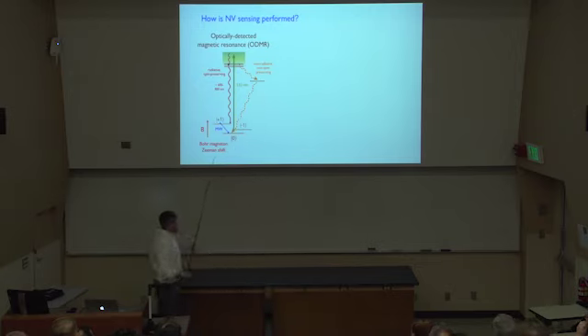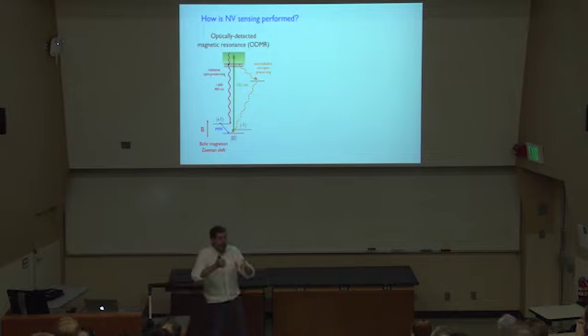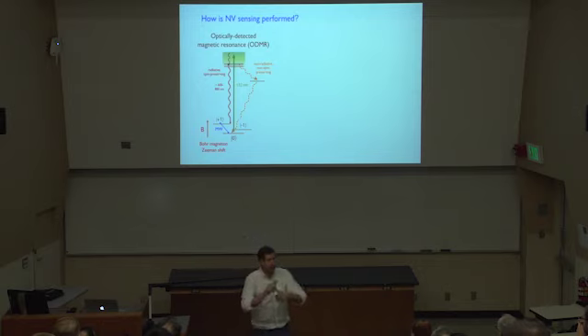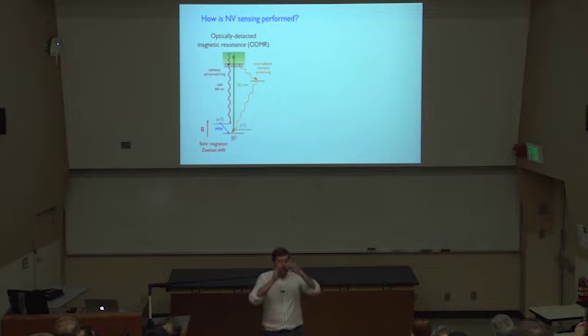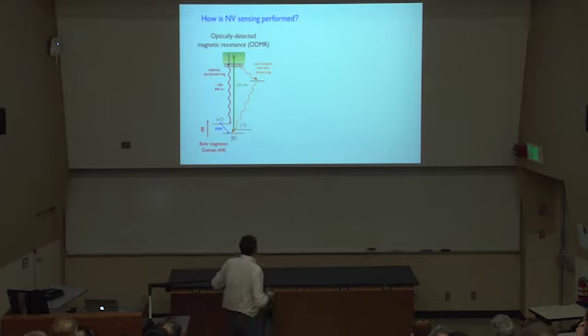For these energy levels, for the s = 1, that means you have an ms = 0 and ms = plus and minus 1 levels, as shown here. And the ms = 0 and ms = plus and minus 1 are split by about 3 gigahertz. They're split by the magnetic dipole-dipole interaction between the two electrons which make up the s = 1 NV. Right? NV is an electron cloud. It's got 2 electrons to first approximation. That's how you can think about it. They spatially orient themselves in this spin symmetric mode here, and you have a dipole-dipole interaction that splits the ms = 0 from the other levels by about 3 gigahertz.